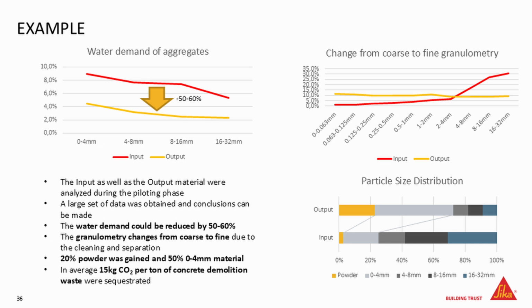Of course, what we do, and that's the diagrams on the right side, is we change the granulometry. You don't get the same granulometry as you put in, because the large aggregates are agglomerates of smaller aggregates and the cementitious material. When you separate them, you get a different granulometry, so we get much more fine content. At the bottom right, you see the particle size distribution of the output material, and roughly 20% of that is powder. Powder is defined as what is transported via the air, roughly smaller than 120 micrometers. Then 50% is the 0 to 4 fraction, the sand fraction, and roughly 30% is coarser aggregates.